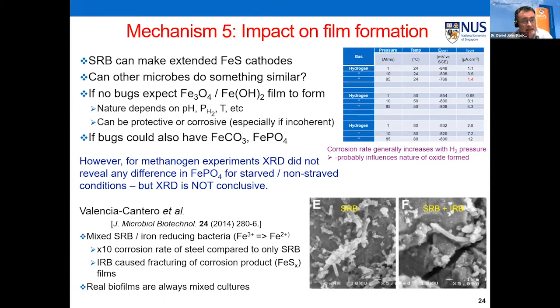The other mechanism that I think is possible is impact on film formation. We know SRB can make extended iron sulfide cathodes. Could other microbes do something similar? Could we have bugs that make an iron carbonate or an iron phosphate surface? We were fairly certain, when I go back to this data, that higher hydrogen pressures caused increased corrosion rates. We thought it probably influenced the nature of the oxide film formed. If the oxide film is less protective, then you will get a higher corrosion rate.